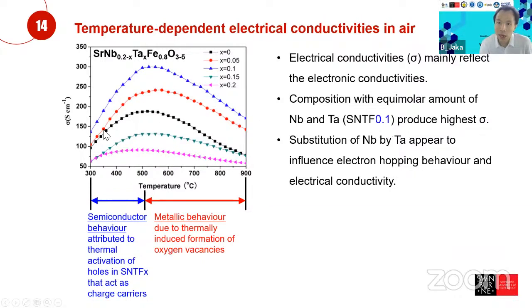Okay, we can see that the highest electrical conductivity is obtained when we put an equal amount of the niobium and tantalum into the B sites of the perovskites in here, which is exhibited by x equals 0.1.